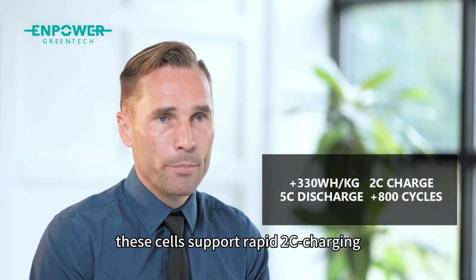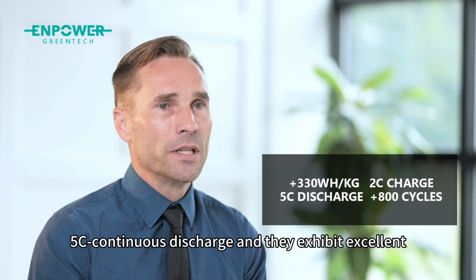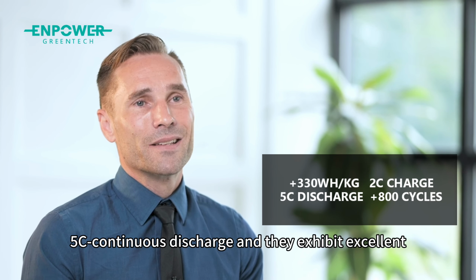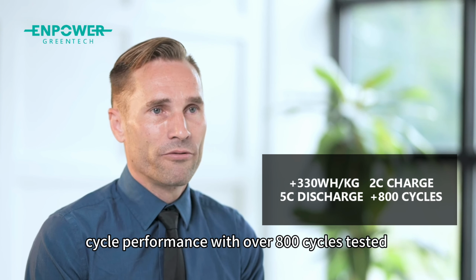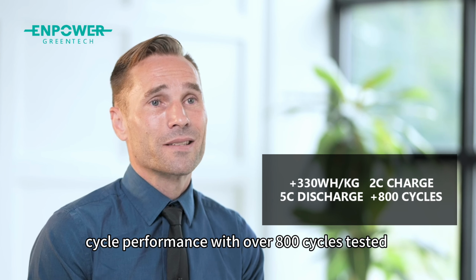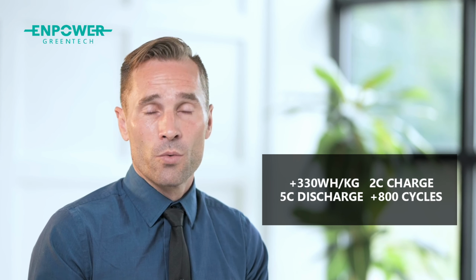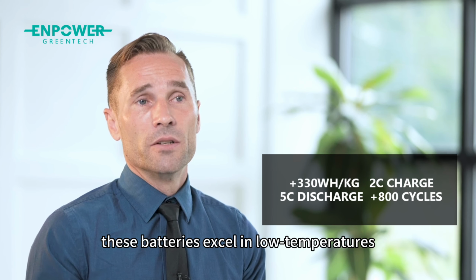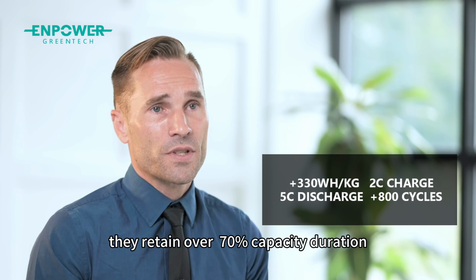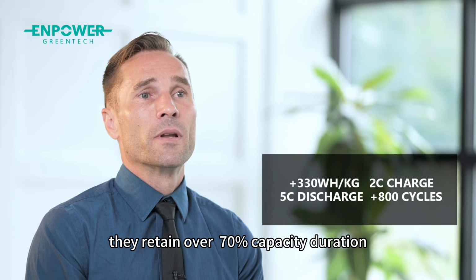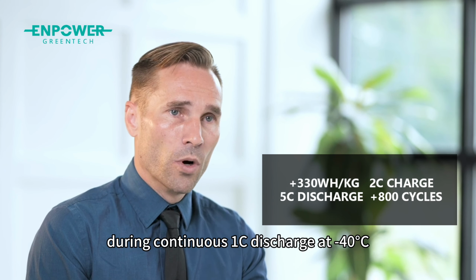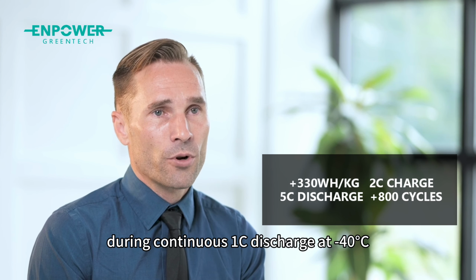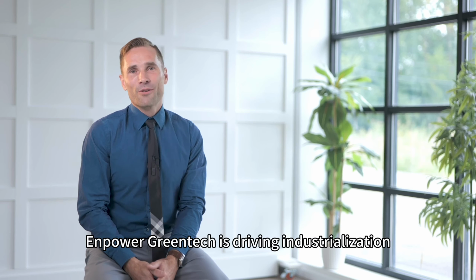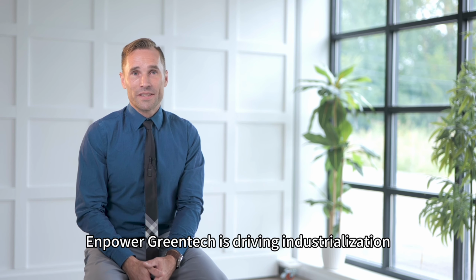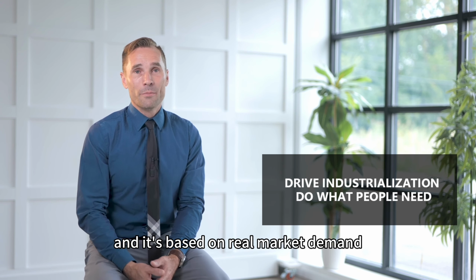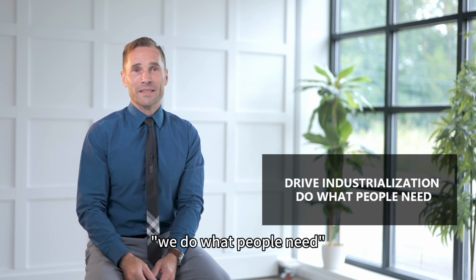These cells support rapid 2C charging, 5C continuous discharge, and they exhibit excellent cycle performance with over 800 cycles tested at zero pressure. Regarding conditions, these batteries excel in low temperatures. They retain over 70% capacity during continuous 1C discharge at negative 40 degrees centigrade. Enpower Greentech is driving industrialization, and it's based on real market demand. We do what people need.